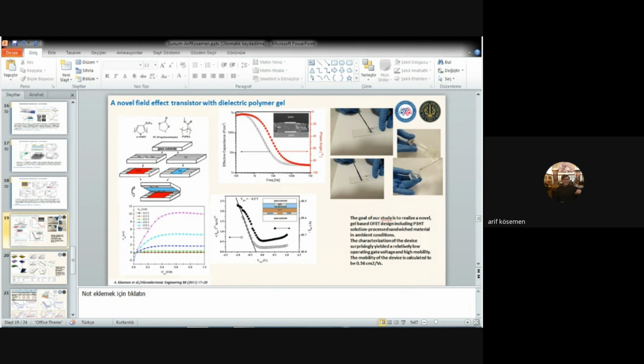And how can we apply this material? First of all, we separately coat the source and drain electrodes and the gate electrode on the glass substrate. We use silver electrodes, and on the source drain electrodes P3HT is coated as the active layer by the spin coating method. This gel is sprayed with this bottle on the gate electrode. Then we sandwich the gel between these two substrates, and surprisingly we get a very low operation voltage organic field effect transistor with this structure.